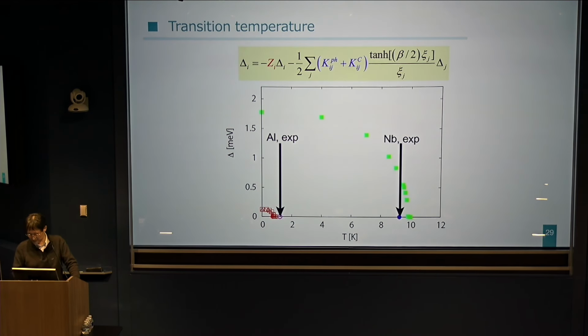So we can construct these three factors, and this is the benchmark calculation for aluminum and niobium. Here I plotted the size of the gap function as a function of temperature, and we see that in the case of niobium, it becomes 0 at around 10 Kelvin, and aluminum at 1 Kelvin. And in both cases, the agreement between theory and experiment is very good.